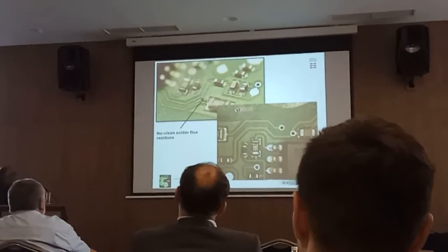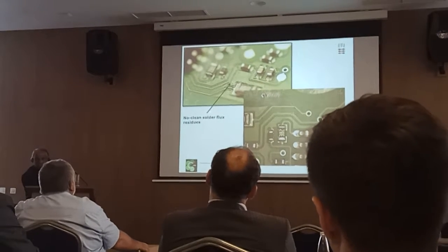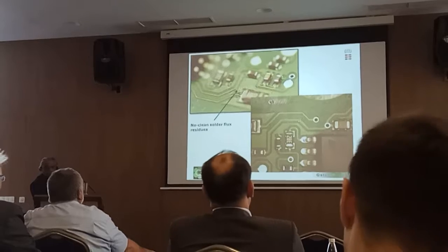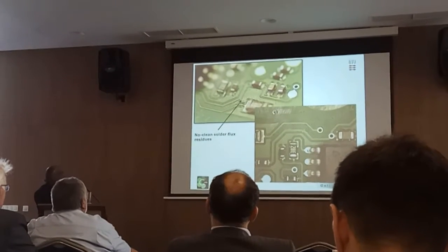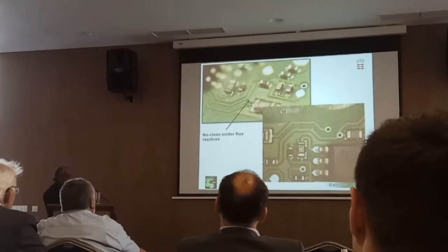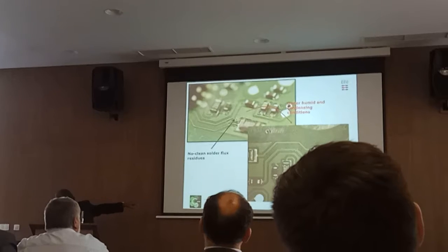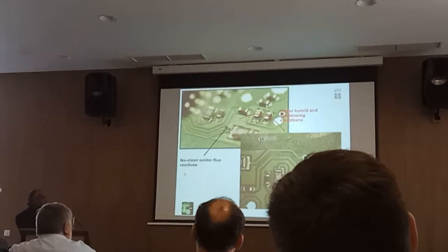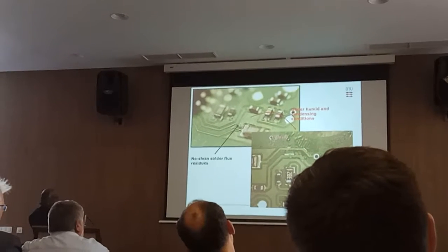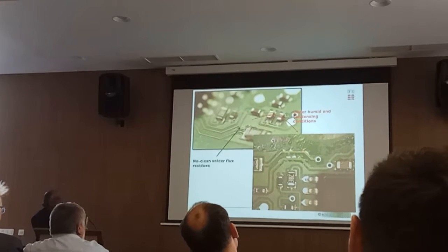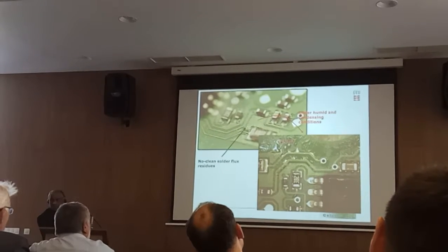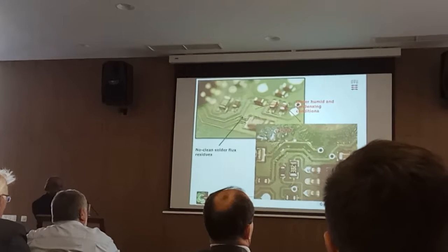Another factor is contamination of the surface — flux contamination, where the residues are sitting on the surface. These residues are ionic residues, which means they can easily absorb water. To show you that — if this PCB is exposed to different conditions, you can see that the places where there is some residue are preferentially absorbing the water from the humidity and forming the water layer, while all other surfaces show no water layer. This means that these residue areas are acting as hygroscopic areas which can easily form a thick layer of water.